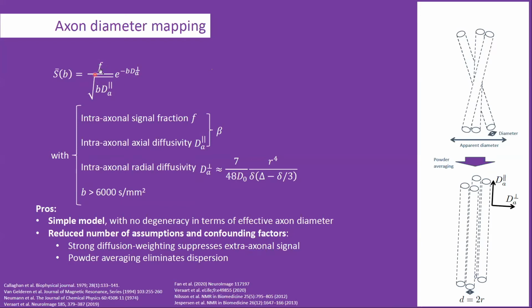We've got this intra-axonal signal fraction F. We've got an intra-axonal axial diffusivity, and both combined result in a prefactor beta. But our focus is on relating this intra-axonal radial diffusivity to the radius. Now, this model assumes there are no other compartments contributing to the signal. That means we are assuming that there is no contribution of the extra-axonal space.